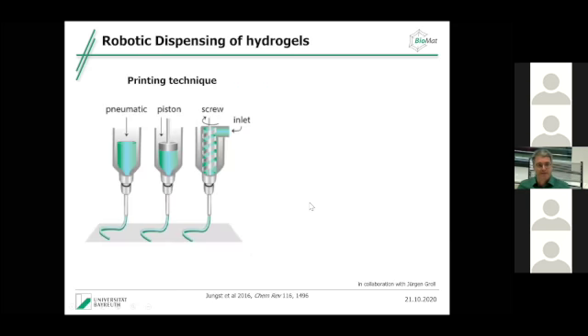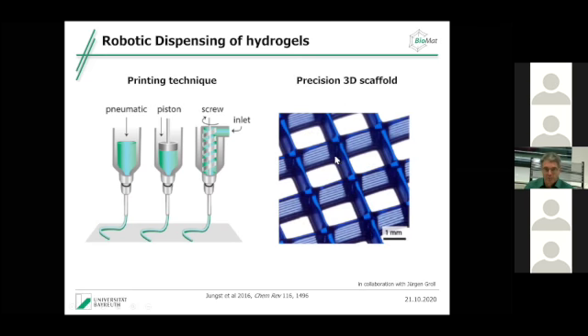The next step was, can we actually give these hydrogels also specific shapes? And for that, we tested robotic dispensing. So what you do is you put this hydrogel in any kind of capillary, and then, either pneumatic or with a piston or with a screw, you press it through a needle. And if you have a good hydrogel, it starts to flow when the pressure is set on, and it immediately hardens as it comes out. So this is called the shear thinning behavior. And then you actually can make precision 3D scaffolds.